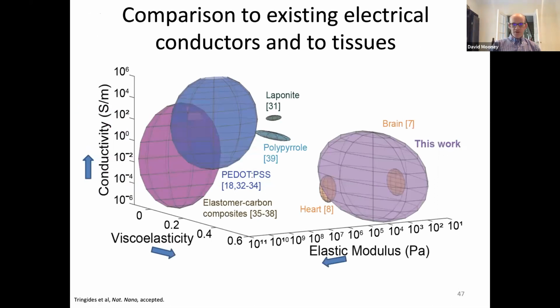With this approach, when we construct the entire device, we can match the mechanical properties of soft tissues very nicely. So this is just a demonstration of the current materials that are out there today, and then these new materials that we're designing, where we're looking at the conductivity on one axis, the viscoelasticity on a second, and the elastic modulus on the third. And you can appreciate all the existing materials do not mechanically match well, for example, the heart or the brain, which are shown here. And the devices we're creating have properties that overlap with these types of soft tissues.